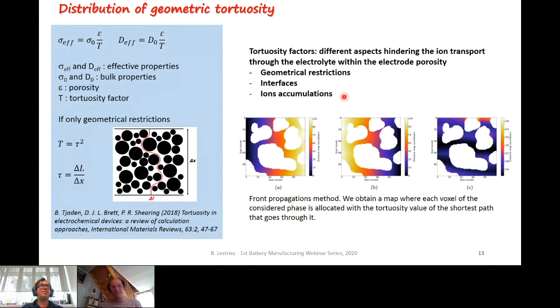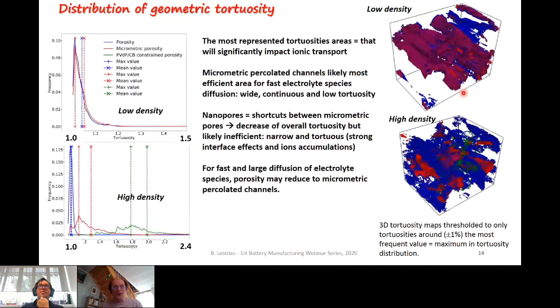And you know that ions can adsorb at the surface of solids, and also ions can accumulate at bottlenecks between large pores, for example. So here, on the FIB-SEM volumes, we have focused on the geometrical tortuosity. So it was calculated through a front propagation method. And in the end, we obtain a map where each voxel of the considered phase is allocated with the tortuosity value of the shortest path that goes through it. So on the following slide, we will first look at the distribution of the local geometric tortuosities.